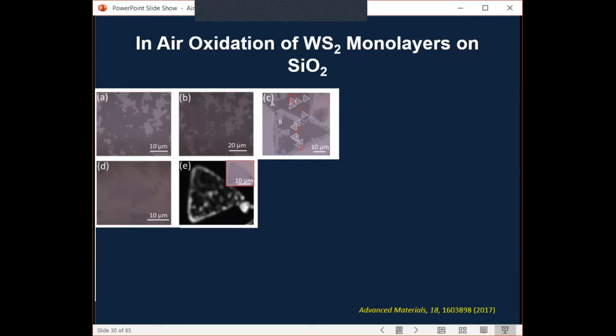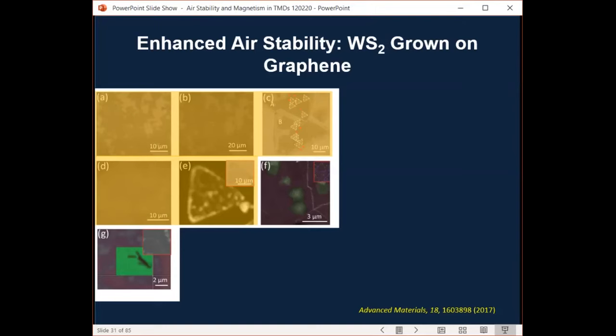So let me continue here. So figure D here is a sample grown on oxide. This is tungsten sulfide grown on oxide after four months. So you just put the sample in the air, four months, just doing nothing there. But what happened here is D is totally oxidized. And this is confirmed in figure E. This is a Raman mapping where you see the complete quenching, Raman quenching here indicating that the material is almost fully oxidized. So there's no tungsten sulfide anymore. All right. So what happens here is, so now we tested another sample that we grew on graphene this time. Same tungsten sulfide grew on graphene. Grown graphene here. And this is a false colored imaging, figure F here. This is false color SCM image of epitaxially grown tungsten sulfide monolayer on a graphene substrate. Here, the graphene was transferred to an oxidized silicon substrate before growing tungsten sulfide atop. So you first make the graphene, then we grow directly on the graphene. So the same image was again, taken after four months, as like D and E case, F and G. Also, this is from the sample after four months of exposure, but you can see the clear difference because you see the Raman quenching from figure G along the grain boundary only, which contrasts with the tungsten sulfide grown on oxide that was fully oxidized for the same duration.